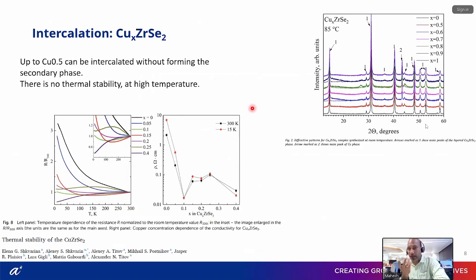There's another: we do in MoS2, we see the intercalation, right? These materials are able to, without changing any phase, incorporate copper up to 50%, like 0.5. Whereas above 0.5, they found a secondary phase, like a pure copper phase. So you can intercalate and change the transport, but it's old. I don't like to intercalate, I'm just presenting. Intercalation is not stable. Whenever it is irreversible, and when you heat it, it makes an alloy.